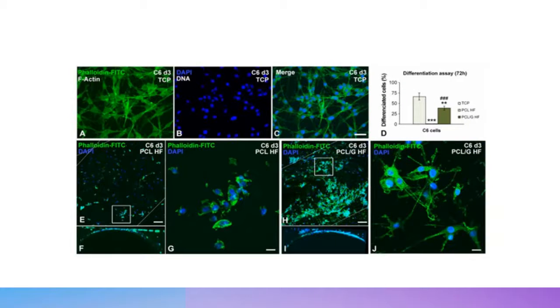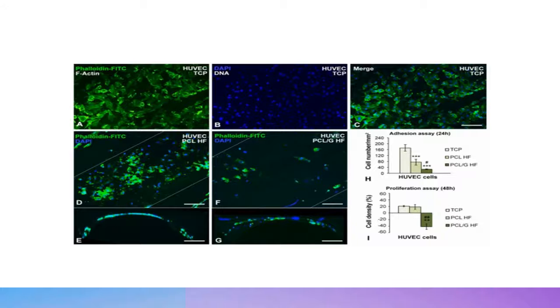Figure 6, images of confocal microscopy for the study of astrocyte differentiation for 72 hours on TCP, PCL, and PCL graphene substrates. Cells had dramatically reduced their cell and nuclear size in addition to presenting numerous cytoplasmic projections. Last is Figure 7, mosaic cell culture of HUVEC endothelial model over TCP, confocal microscopy images of HUVEC cells grown on the surface of PCL or PCL graphene membranes in hollow fiber configuration 24 hours after seeding.